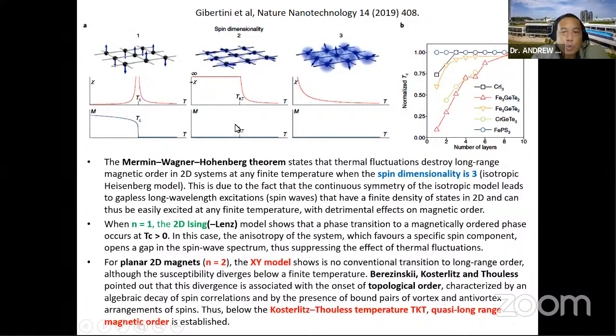you can get a quasi long-range order due to the physics that was discovered by the recent Nobel laureates Berezinskii, Kosterlitz, and Thouless, right? So they proposed this temperature, this Kosterlitz-Thouless temperature, T_KT over here, where you can see some quasi magnetic order and some transition in this case because of the topological properties of the 2D planar magnets.